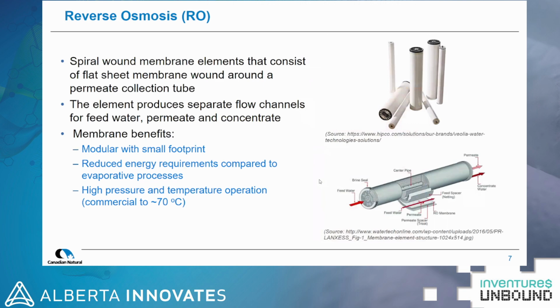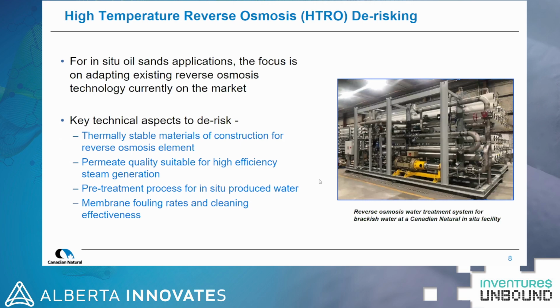So we want to adapt this technology for our applications. We don't want to reinvent the wheel. We want to adapt what's on the market today. The things that we need to de-risk: we need to identify thermally stable materials of construction. We want to operate up above 100 degrees C. We want to ensure the permeate quality is suitable for higher efficiency steam generation. We need to come up with a treatment process which is tailored to our in-situ produced water and at the same time produces high enough quality water to feed into the RO. And then like any membrane in an industrial application, it will foul. So we have to determine those fouling rates and how to clean the membrane.